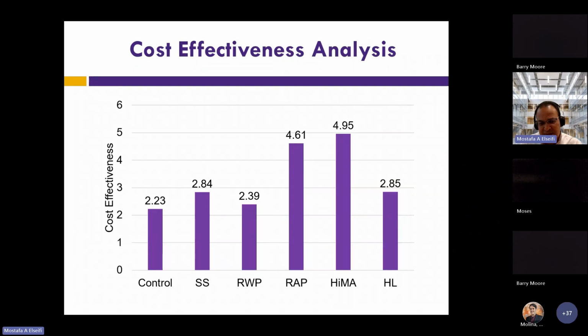So this slide is, in my opinion, the best, most important slide. Again, we said that the cost of HiMA was slightly more than the PG 76-22, but when we looked at the performance as compared to the cost, the best two performers were the HiMA and the RAP mix. And again, this accounts for both the cost of the mix and its performance. It was followed by hydrated lime and steel slag, then recycled waste plastic, and finally the most costly mix when you look at the performance is the control mix.